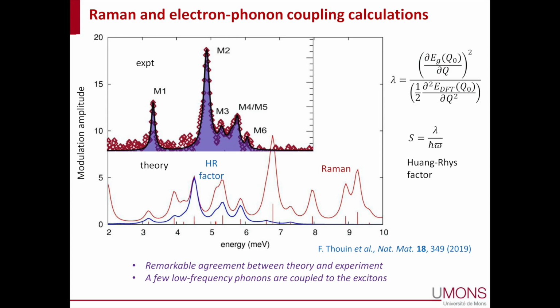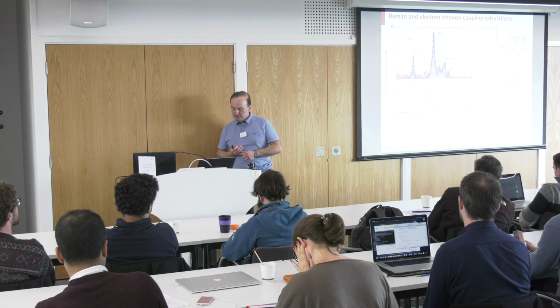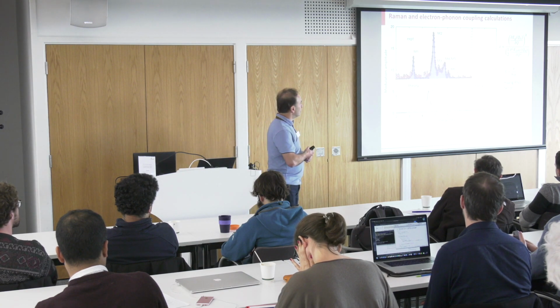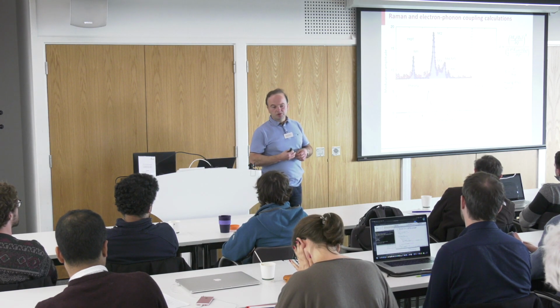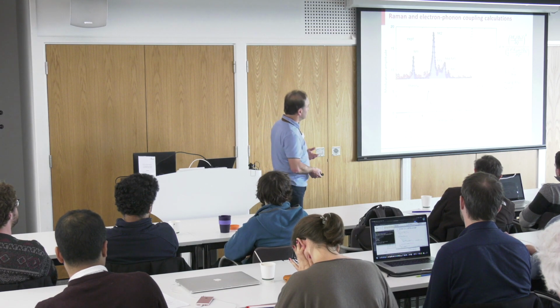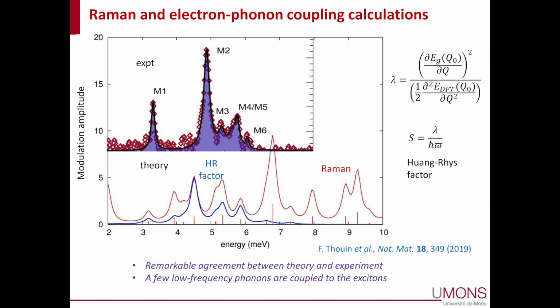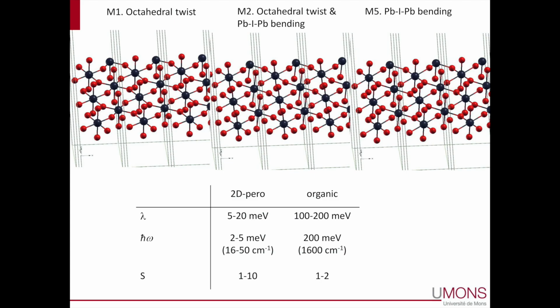And we tried to model this using a very simple model. We took a large supercell of this 3D perovskite, computed the normal modes, distorted along the different normal modes, and calculated the electron-phonon coupling interactions. And to our surprise, the blue line here is the calculated spectrum, matches quite well with the experimental spectrum. We see those four modes that are important, that modulate the band gap. And we can, of course, look at what they are. Maybe there's some animation here.